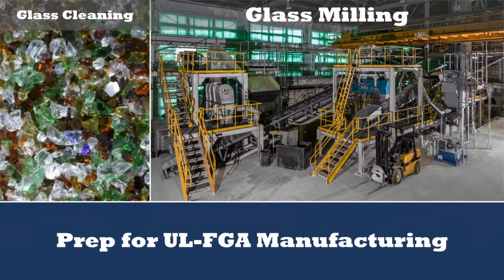And so the next step in our process, our glass processing, is that we need to take these bits of glass cullet that are generally coming to us, about 3/8 of an inch in size. We need to take that down to a very fine powder. I liken it to the all-purpose flour that you would bake with. It looks very similar to that. The particle size is about 65 microns and finer.